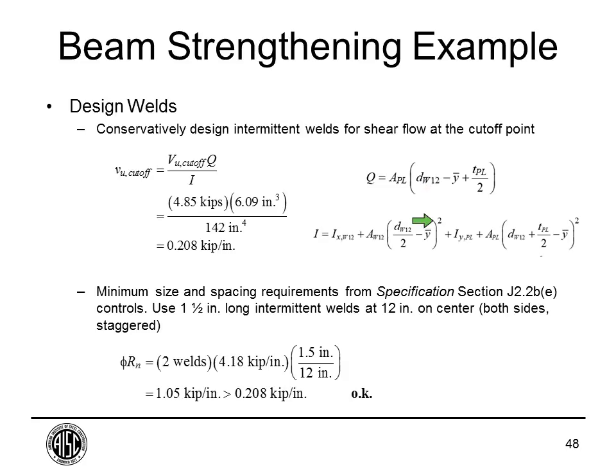The centroid is not the same thing as the plastic neutral axis. So from this equation, we find that we have a shear flow of 0.208 kips per inch. So we need to design our intermittent welds between the terminations for that force. From specification section J2.2b, part E, it gives us some minimum requirements for weld sizes of 1.5 inches long. So we'll consider 1.5 inch long intermittent welds at 12 inches on center, both sides staggered. We calculate the strength of that weld. We get a value of 1.05 kips per inch, which is quite a bit greater than the required strength.